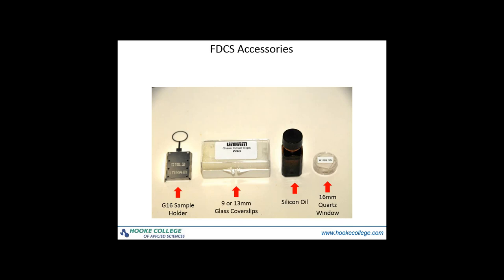The way that you would sample load is you would first introduce the sample holder into the stage. We will then place a single drop of silicone oil onto the block inside of the ring. Once we place our 16 millimeter quartz window, which is our substrate, the oil fills in underneath that 16-millimeter quartz window, and therefore you have even thermal contact from the block onto the substrate. So in case there's any imperfections on the quartz cover slip, or if there's any micro scratches on the block, all of that gets filled in with the oil, so you have that even thermal contact.